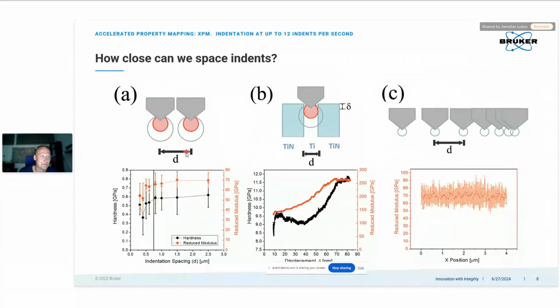In this case, if you change the distance, the spacing between the indents, you see how the hardness and modulus values change with the spacing. Of course, if you deform your surface with your indents and you produce an indent next to each other, the contact area is also affected by the plastic deformation next to it. This has an influence on the reduced modulus as well. You see that there is some kind of threshold where there is no influence, so you get the plateau. Basically the properties are not changing anymore with the indent spacing. This would be the ideal spacing for your map.